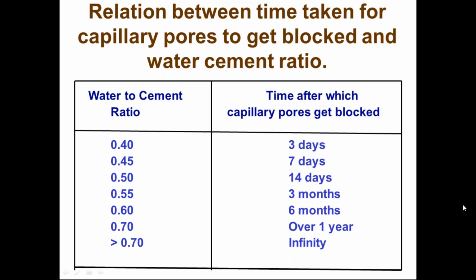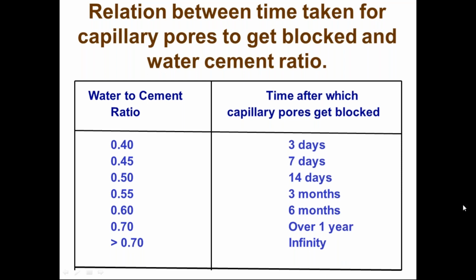Next. Another very important factor which is to be seen is water cement ratio versus the time after which the capillary pores get blocked. If you notice around 0.4, if the water cement ratio of the concrete mix is 0.4, then within 3 days the concrete becomes virtually impermeable because the capillary pores get blocked very fast.